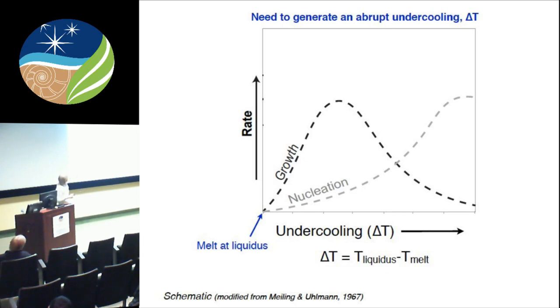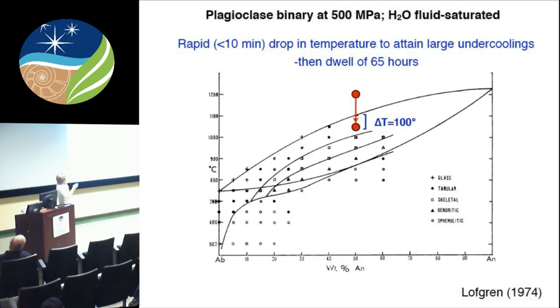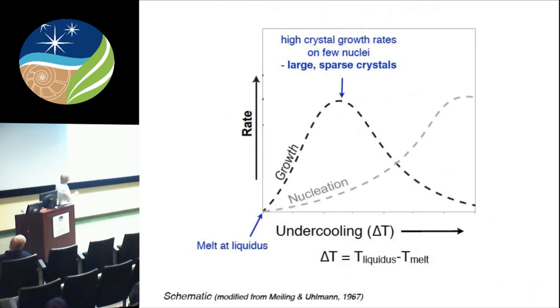But what Lofgren did is he was working on the anorthite albite binary, and he was up at high pressure, water saturated, and he started above the liquidus and just dropped the temperature, so it was 100 degrees below the liquidus down to here. He did that within 10 minutes and then held it. And he ended up with those big crystals I just showed you. So what he was able to do was get an undercooling where he had low nucleation rate and a high crystal growth rate. So all that high crystal growth could get concentrated in a few nuclei.